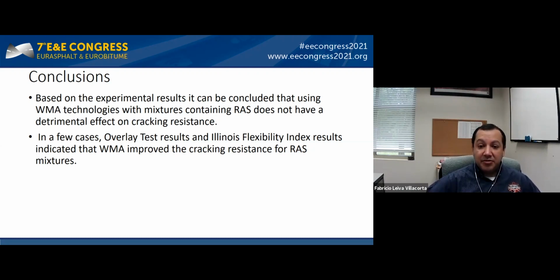In fact, we were able to observe that in most cases, warm mix technology helps increase cracking resistance, and that's promising in regards to these different materials, not only for RAP that has been observed in the past in the literature. There are many different publications that already consider the combination of warm mix and wrap as a way to go in terms of performance. But now we were able to observe that that can be the case when we add recycled asphalt shingles. And with that, that's all I have, and thank you very much.